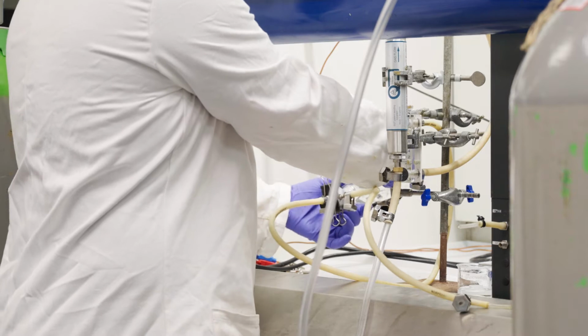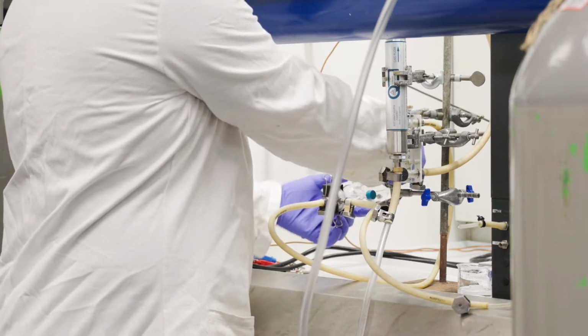So one of the things that we've been looking at is various different coatings we can put onto the surface of the copper particles we're using. One of the things we've been working with is a porous polymer coating. So the idea is you have a very thin porous layer over the top of the particles. Those pores are so small that they stop bubbles forming.